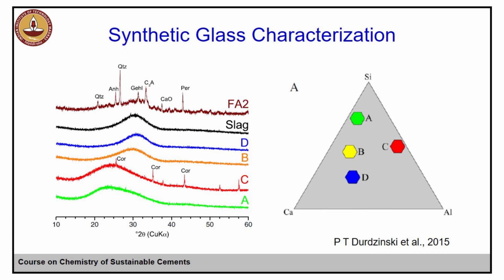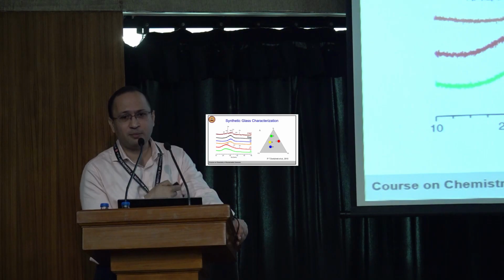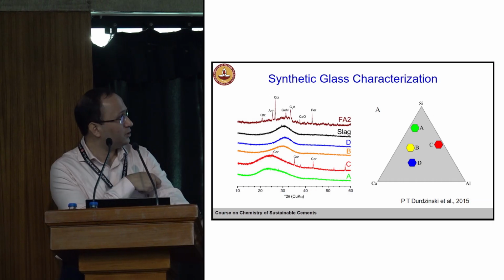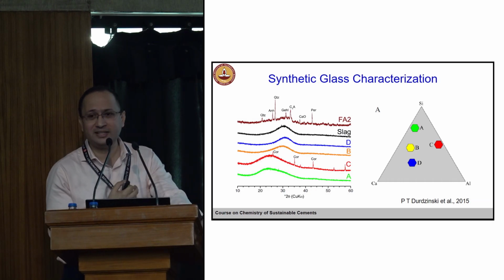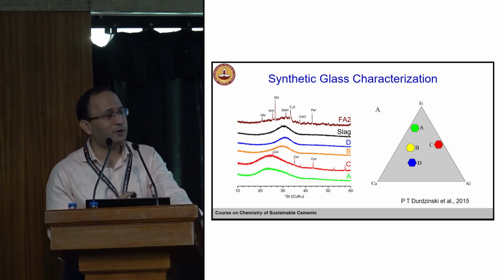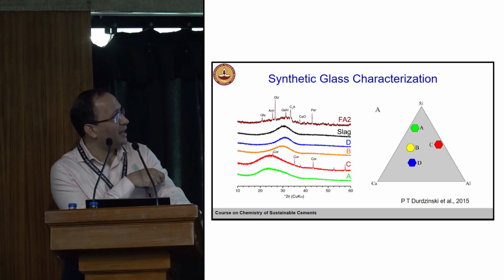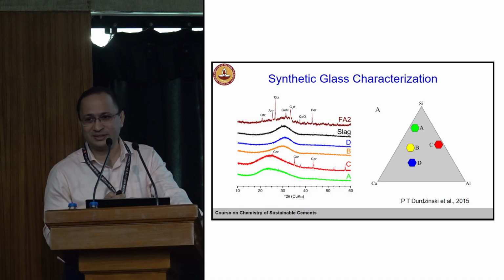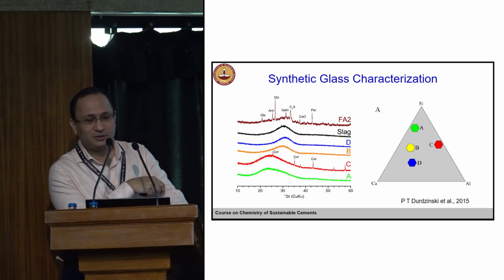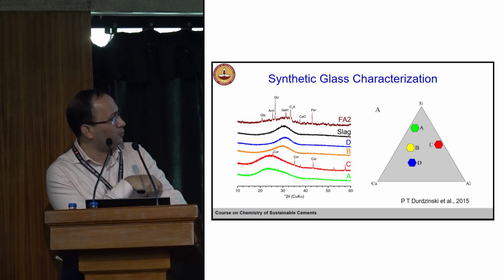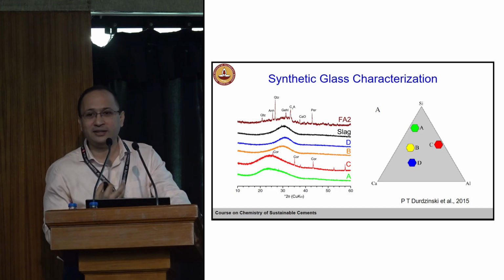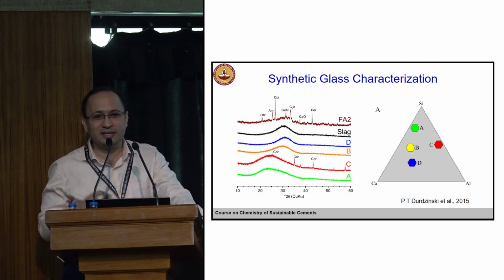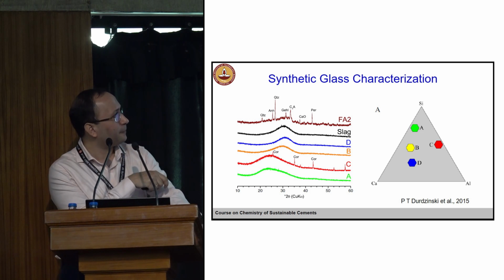In this X-ray diffraction, the hump typically depicts the amorphous nature of a material. So you see an amorphous hump. That shows that whatever synthetic material we are talking about has amorphous content. But you also notice there is a difference in amorphous nature. All are different. Here you see the hump between 20 to 30. In this case, it is shifted towards the right. So it shows that the amorphous phase changes depending on the composition.